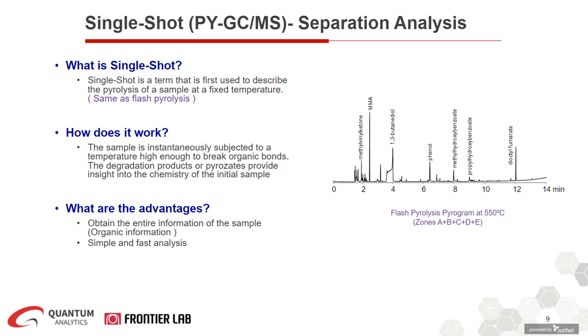And then we perform flash pyrolysis, and the pyrogram obtained from the single shot corresponds to all 5 zones in the EGA. So all the additives and polymeric fragmentation come in one pyrogram, as you can see here. What are the advantages of single shot? Well, obtaining the entire organic information of the sample in one pyrogram, which is a pretty fast and simple analysis.